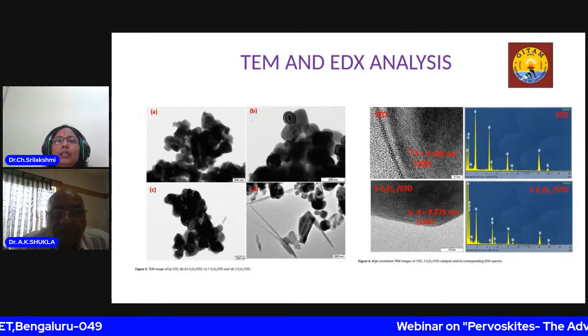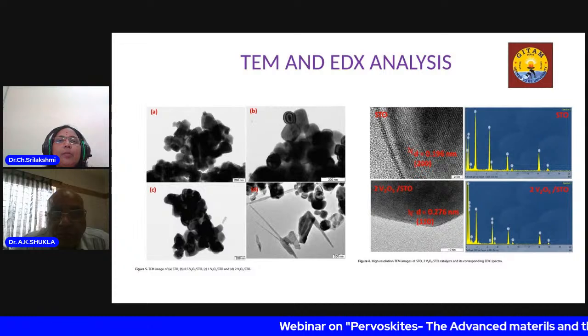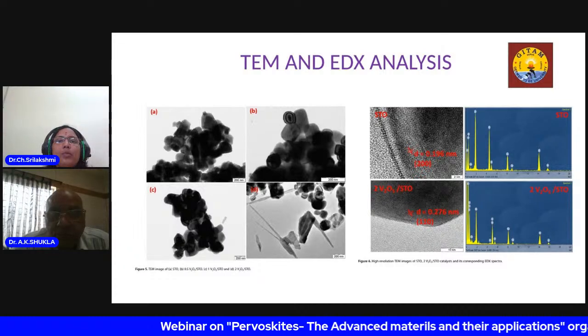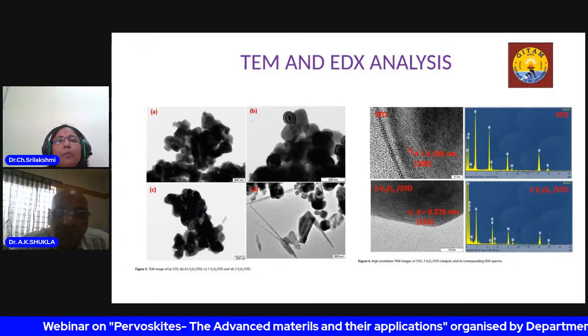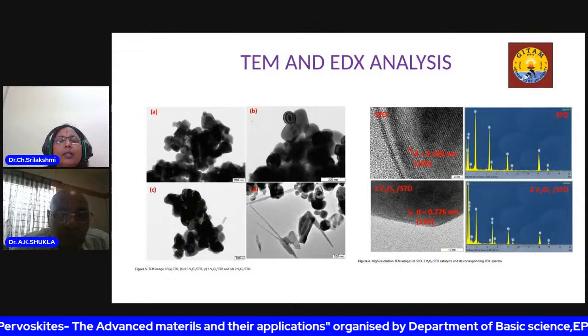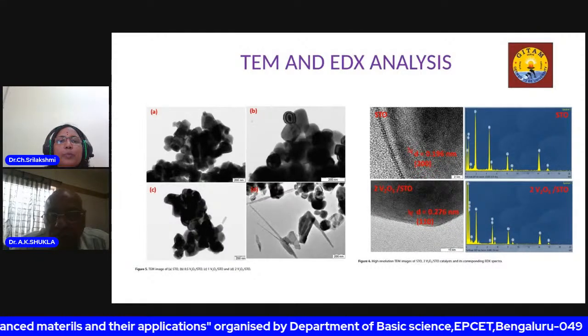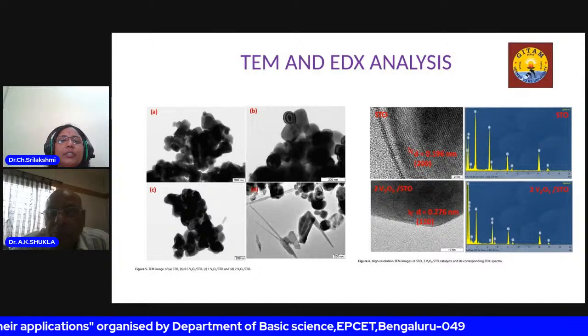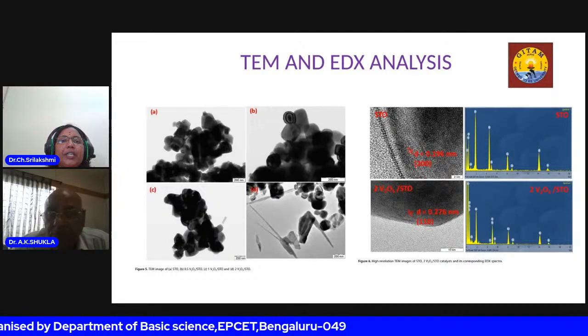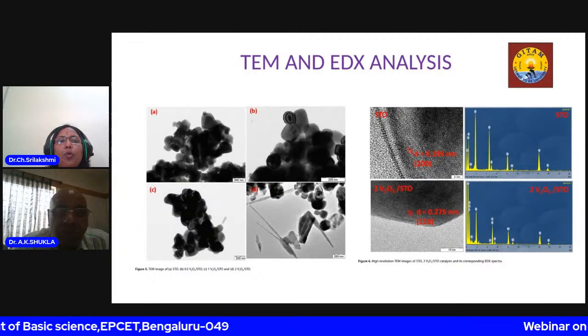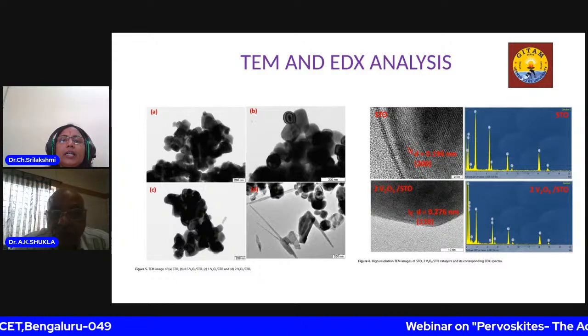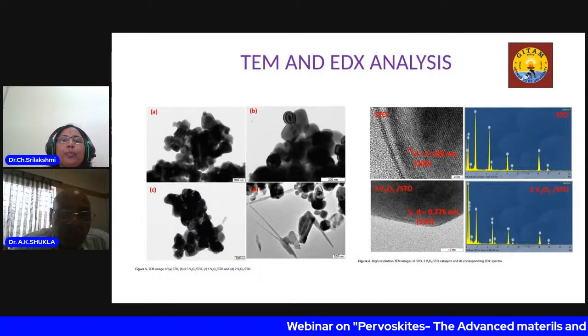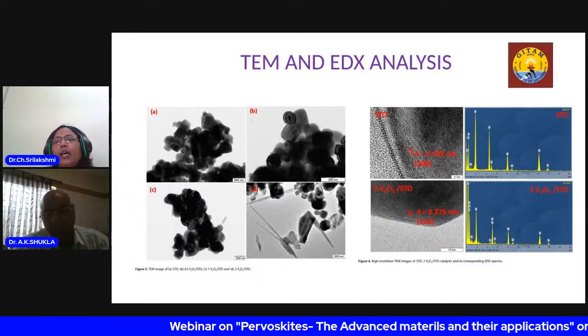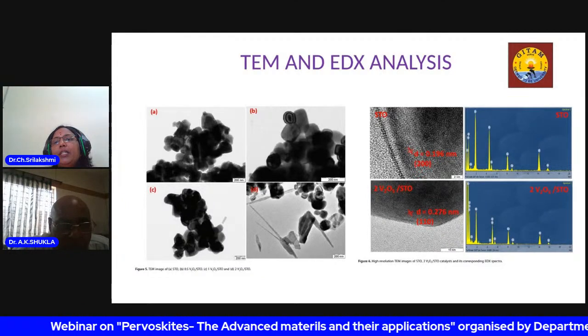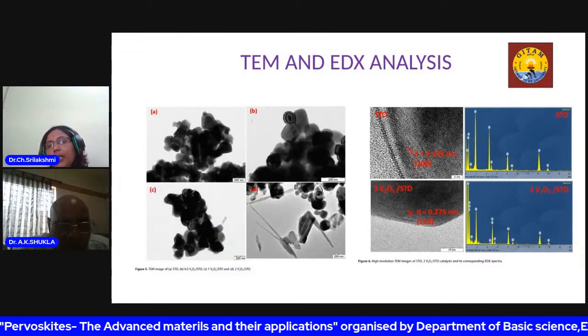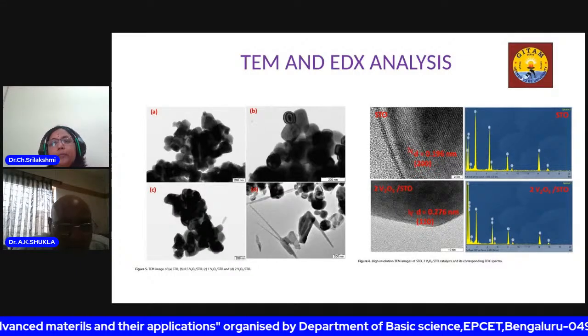So these are the TEM and EDAX again. You can see the morphology: the samples contain spherical particles and cubic nanoparticles, and the morphology is changing from spherical to plate-like structures. The morphology change initiated at 1 weight% vanadium on strontium titanate, and there is a complete, about 80%, change to plate-like structures here. Again, the incorporation of vanadium is confirmed through TEM and EDAX analysis.